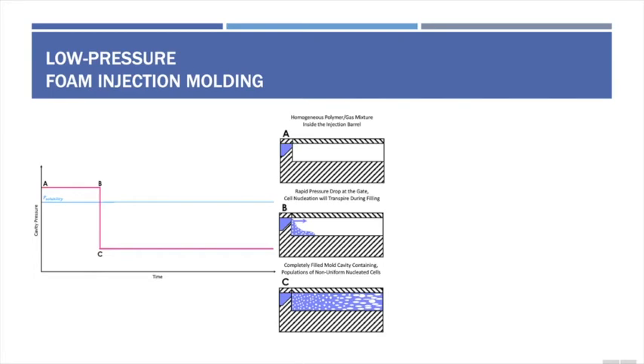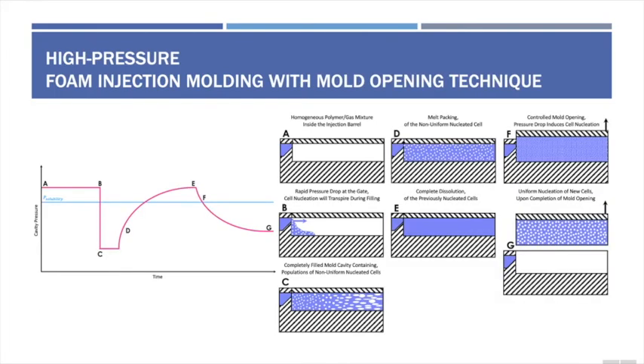The bubbles are then nucleated within the mold cavity, and this will form fairly non-uniform parts, but it will have very short cycle times. In contrast, high pressure foam injection molding includes the extra step of packing before the final foaming occurs. This packing allows the nucleated gas to redissolve before mold opening to allow the gas bubbles to expand. This produces parts that are very homogeneous with enhanced mechanical properties. However, this technique does involve the extra dissolution time, which is approximately 20 seconds, which is extra compared to low pressure injection molding.